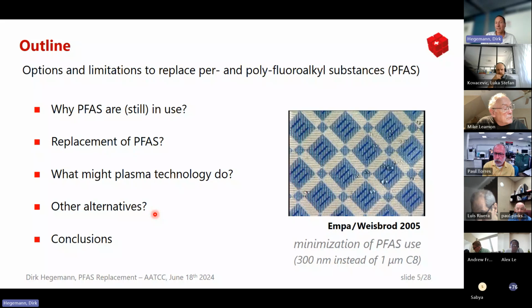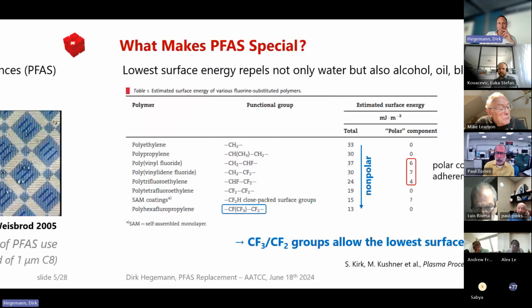Are there other alternatives? Actually, what we have done here was in 2005. As Sabia mentioned, I have not been long with Empa, and at that time we were using PFAS, but we replaced the common PFAS, which was typically 1 micron of C8 chemistry, by a different kind of chemistry, only 300 nanometers thick. So we were always aiming at lowering the amount of fluorocarbons used, and we will see later that tendencies go in a different direction.